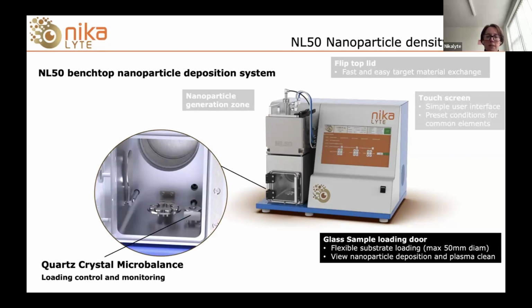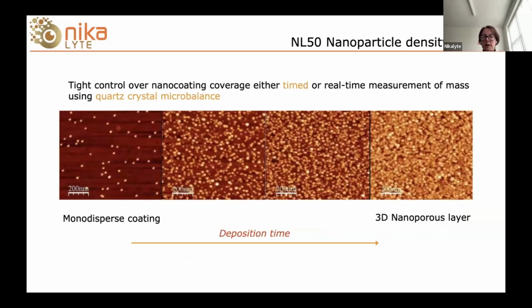The quartz microbalance is a little crystal monitor which vibrates, and that measures the amount of material landing on it. So during the actual deposition process, we are measuring the amount of material landing on the surface in real time. And what that means is excellent control over the density and loading of material on the surface. So it's possible to generate coatings from monodisperse individual nanoparticles, such as this on the left-hand side, right up to 3D nanoporous layers, which are microgram densities or even higher.